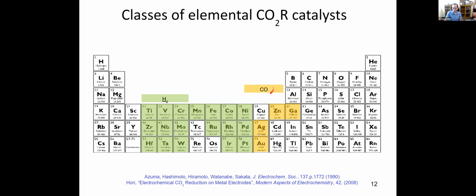There are things that are more valuable than carbon monoxide. If I make it out of tin or cadmium or indium or these others, you get a bunch of formate. That's sort of because the CO2 binds 2 oxygens down. And that's a very interesting behavior. But what's really cool is that there's only one metal that's known to make C1 and C2 products, and that's copper. That's the one I just showed you. That's why we start with mechanisms on copper to understand why is it so special and what's going on.